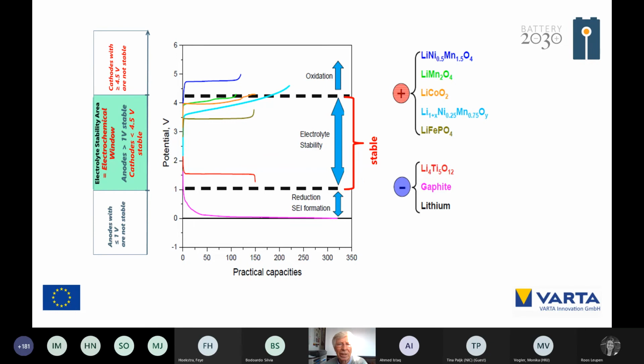And the graphite charge curve you could see here, we are below that 1 volt. That's good because the potential is important for the graphite. And here also we have the lithium in that area. One anode material is outside, or inside better, of the electrochemical window. That is the lithium titanate. You could see that here.